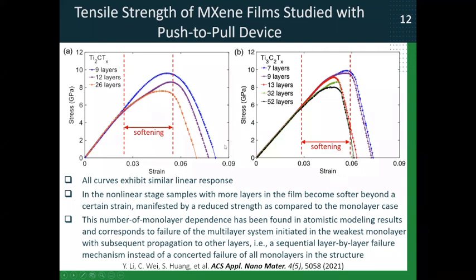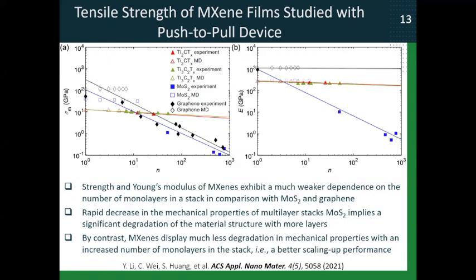Now, this is interesting because it tells us that we can fabricate multi-layer structures based on MXene, and we expect that these structures will demonstrate quite high mechanical properties even when they start to fail, because they don't fail all monolayers at once, they fail in sequence. We can expect that even when they start to fail, they will still maintain quite high mechanical strengths.